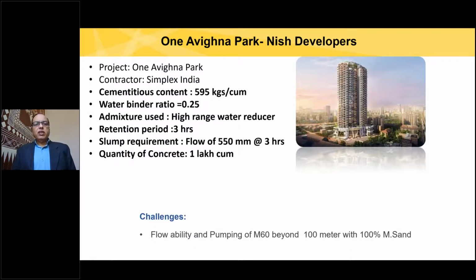Now, this is that One Avighna Park project. It was built by Simplex. They were the contractors. Cementitious material was again 595 kgs. Water binder ratio was 0.25. High range water reducer was used. Flow was 550. And the concrete quantity was 1 lakh cubic meters. So many cubic meters of concrete had to be made with the same consistent property. From batch to batch, you cannot vary.